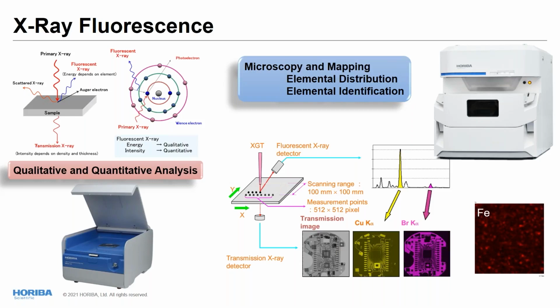Typically, for powders involved in additive manufacturing, a small system, typically a benchtop system able to perform bulk analysis, as shown here, is good enough for the purpose. Having access to a higher-end system, like that one, that allows for mapping, as you can see in some examples here, is nice to provide some nice pictures where you can also see a little bit the heterogeneity or homogeneity of the powder.